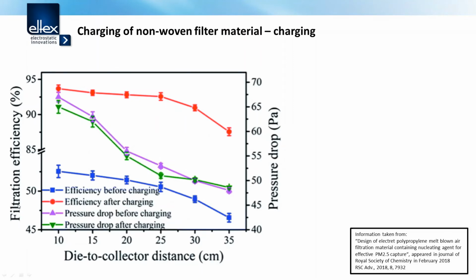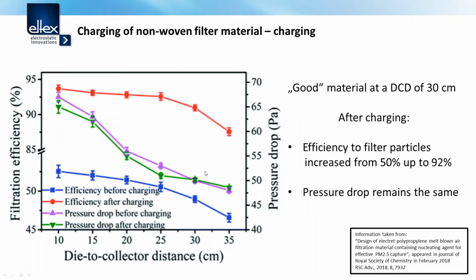You see here the filtration efficiency. The efficiency before charging, the blue line, with the DCD from 10 to 35 is getting smaller, decreasing a little bit. But after charging, you have here a very high efficiency of the filter. And the pressure drop is almost always the same, is getting a little bit better with a higher DCD. So a good material at a DCD of 30 centimeter has after charging an increased efficiency of the filter from 50% up to 92%, and the pressure drop almost remains the same.